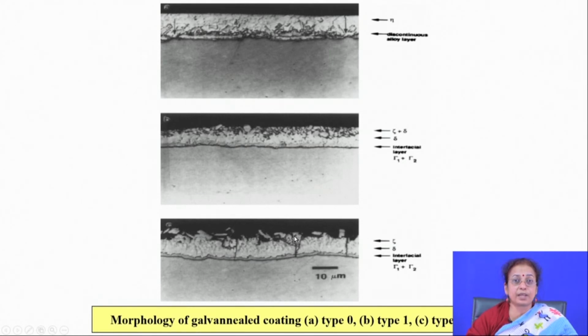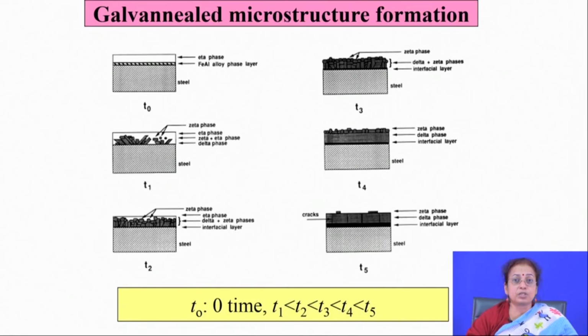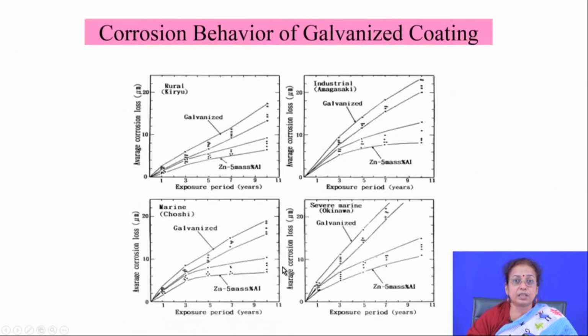So, with optimum timing you can have the typical base microstructure, consisting, for example, at the end of the galvannealing, of zeta phase on the top, then delta phase in the middle and a very thin interfacial layer. So, this is nothing but a typical annealing operation to homogenize the microstructure and also to release the stress which is developed by the galvanizing process.